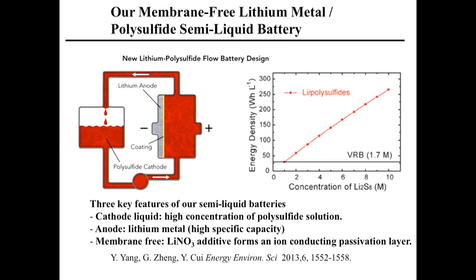So you take lithium metal, you flow this liquid in and out of this battery. This is the big tank you store it in. This is a beautiful thing using lithium metal. You don't use 2 liquids, you use 1 solid, 1 liquid. You don't have the mixing problem anymore. You don't want 2 liquids to mix, right? Now the solid reacts with the liquid and produces this yellow color. It's a cell passivation layer. It stops after a while to make this interface stable. It's conducting lithium back and forth. It's your ionic conducting membrane. You get it for free, so you can go to low cost.